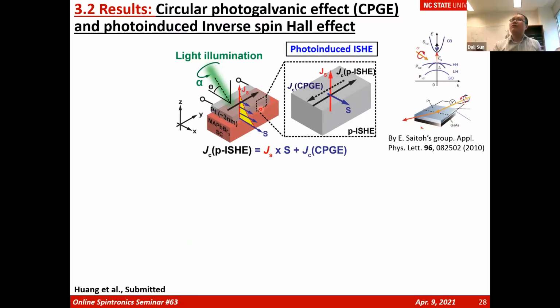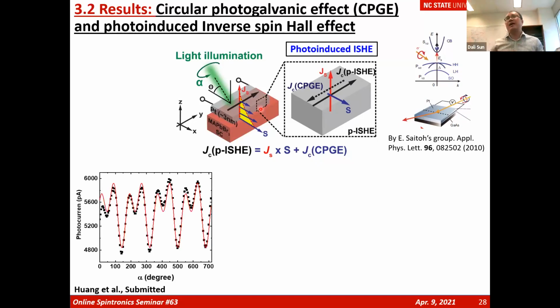The spin current will diffuse into the platinum and convert into a transverse electric field because of the high efficiency of the spin Hall angle in the platinum. If the CPG still exists and we also have the spin-dependent CPG responses, we should observe oscillating photocurrent in the platinum layer. Actually, it's true. We see the oscillating responses in the platinum layer even more pronounced, orders of magnitude stronger than the CPG itself, because platinum has a very strong spin Hall angle, really converting all the spin information into a transverse electric field.